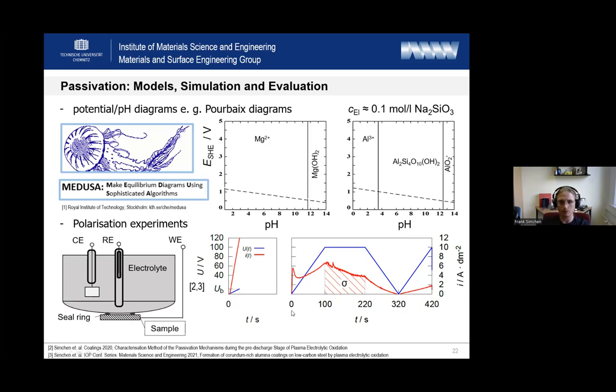So we go from 0 to 100 volt within 100 seconds. And then we can see if we have anodic metal dissolution and electrolysis, or we have passive layer formation. Because in case that we have anodic metal dissolution or anodic oxide formation, just at a low voltage value, we will come to the point that the current flow is too high for the experimental setup and the process is stopped. So maybe here at 12 volt, anodic metal dissolution was dominating, passivation didn't take place, and the process was stopping.